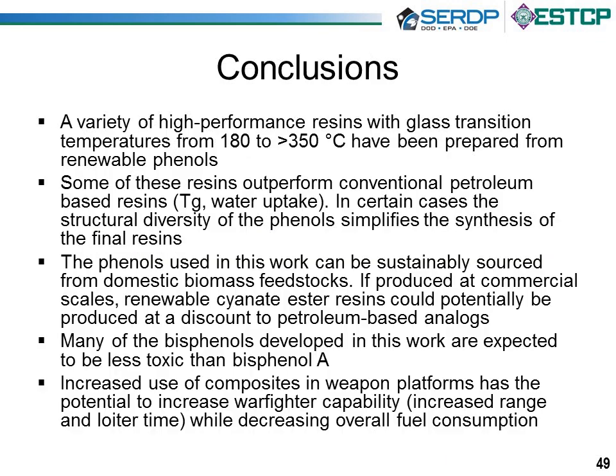So in conclusion, we've synthesized a wide variety of high-performance cyanate ester resins with glass transition temperatures ranging from about 180 to greater than 350 degrees Celsius. Some of these resins actually outperform conventional petroleum-based resins, and as I think I've shown through some of the synthetic slides, the structural diversity of those phenols actually allows for simplified synthetic procedures. All the phenols that I've talked about can be sustainably sourced from domestic biomass feedstocks. If they are produced at large scale, they could potentially be produced for lower cost than petroleum-based analogs.